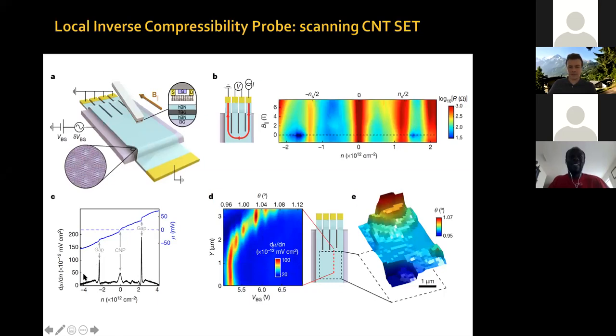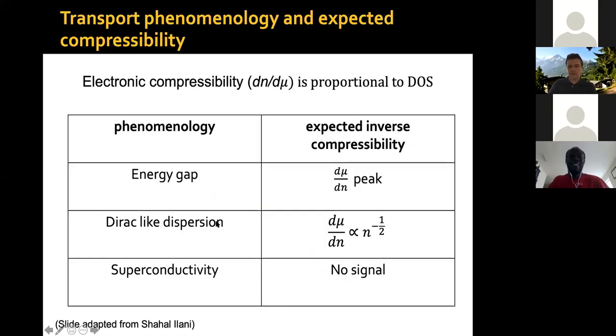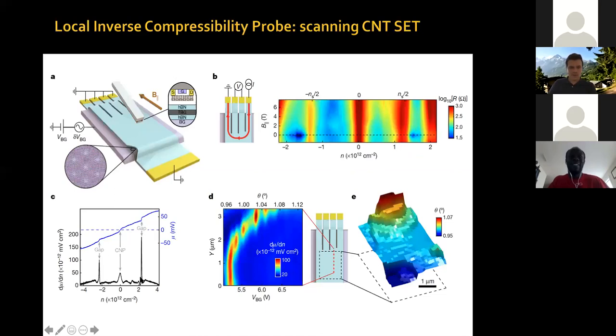This is the band insulator. At charge neutrality, you have this peak with a given decay. That's because you have Dirac bands, and Dirac-like dispersion gives a peak with a decay which goes as 1 over square root of density. So this is what you have here. Now, if you integrate the dμ/dn, you can actually get the chemical potential as a function of density.